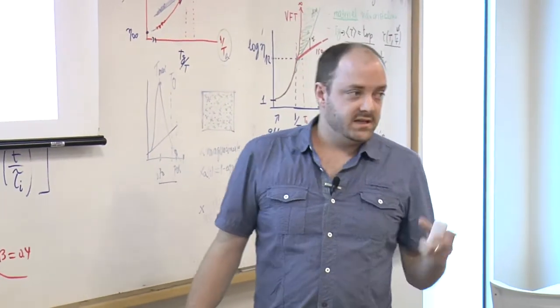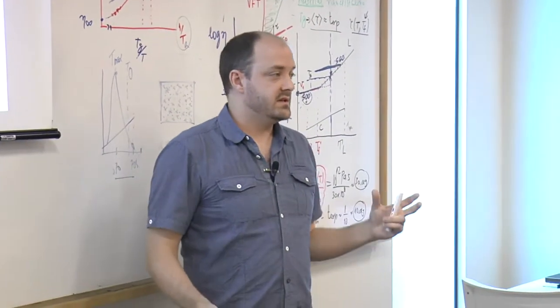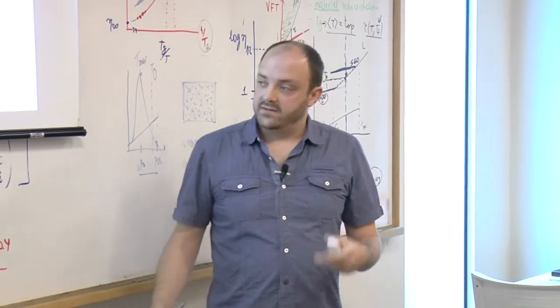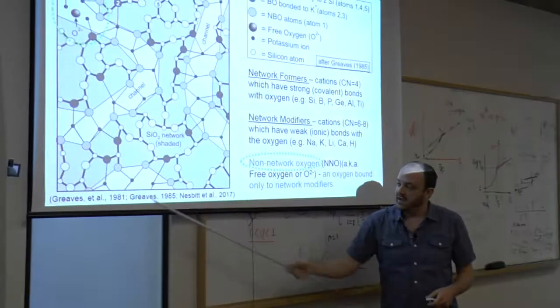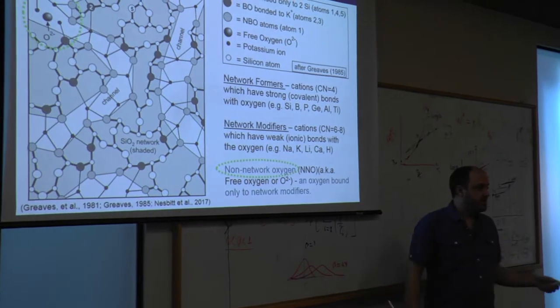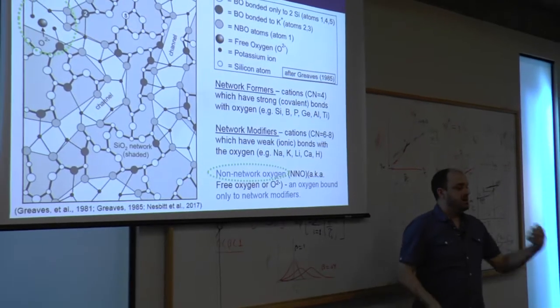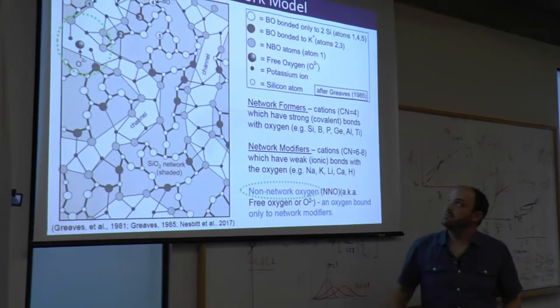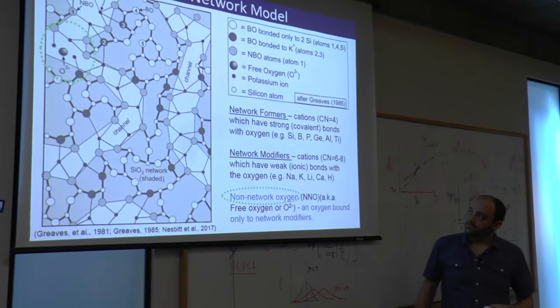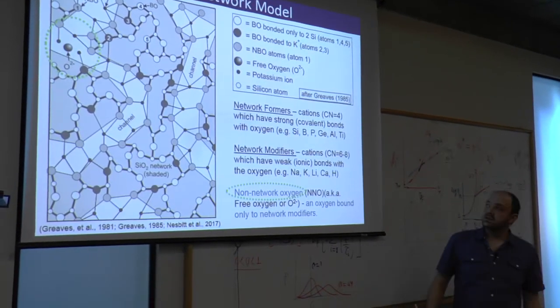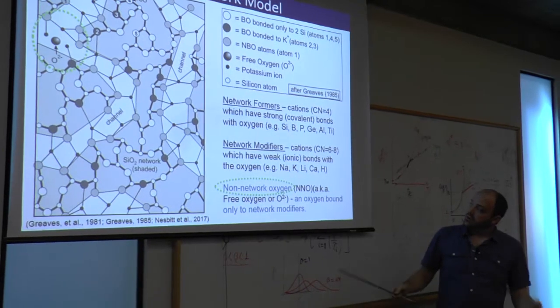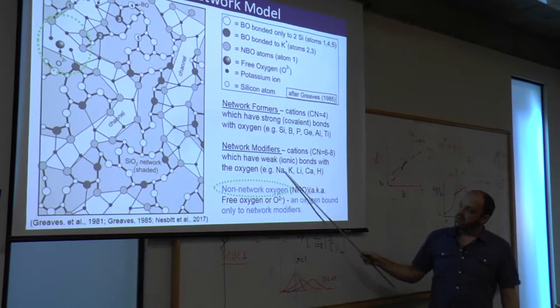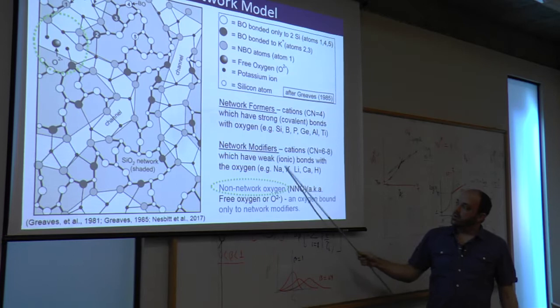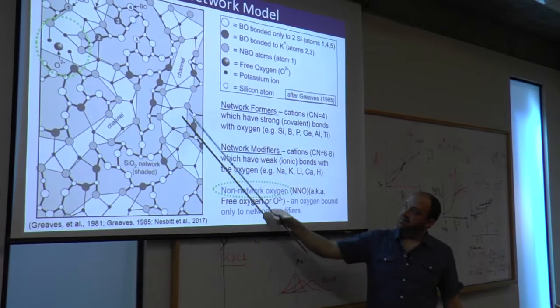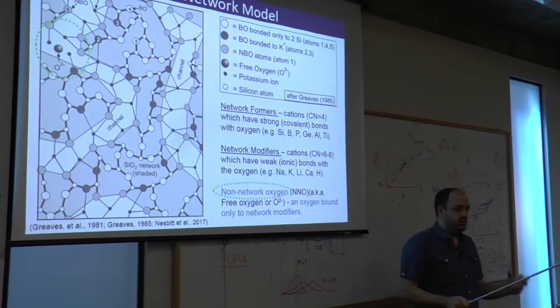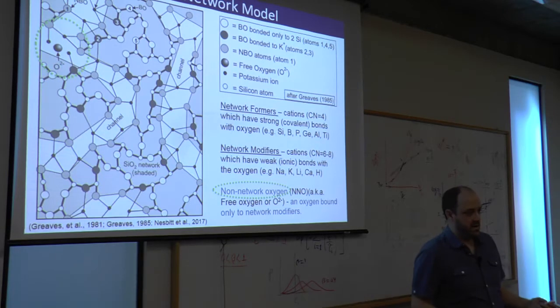So I mentioned Zachariasen. He had this idea about pure silica, SiO2. And it took about 50 years, until the early 80s, for Neville Greaves to come up with the first substantial evolution of this idea, and he called it the modified random network model. He said, as you put in atoms like sodium or potassium, these network modifiers typically have weak, more ionic-like bonds, and so they have to break up this SiO2, these strong covalent bonds, in some way.